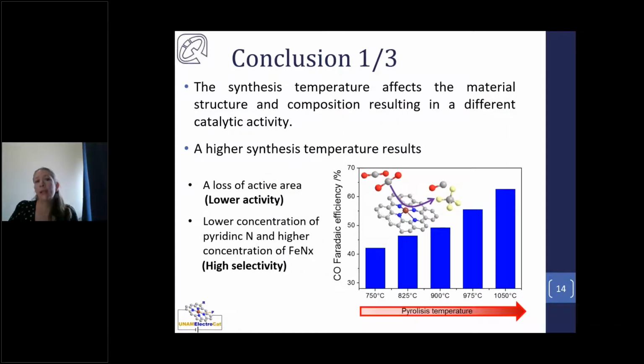So what I hope I show you with this first part of my talk is that these carbon-based materials are interesting catalysts for CO2 reduction, but their catalytic performance is highly dependent on their composition. This can be tuned by the synthesis conditions, in particular the synthesis temperature. When we increase the synthesis temperature, we have a negative effect, the loss of active surface area, which results in a lower activity. But we have a positive effect: we introduce more iron coordinated to nitrogen, which is probably the predominant active site.